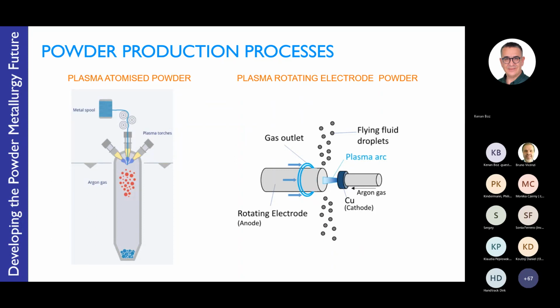So this, again, a very long-established process where, in this case, the raw material is a rotating electrode, and again, using a plasma arc to both melt the raw material and also to provide gas to create the particle surfaces. And of course, because it's rotating, the forces involved spin off the powder particles, and then they're captured in a kind of cylindrical construction. This process typically produces very spherical powder and generally of a coarse fraction.